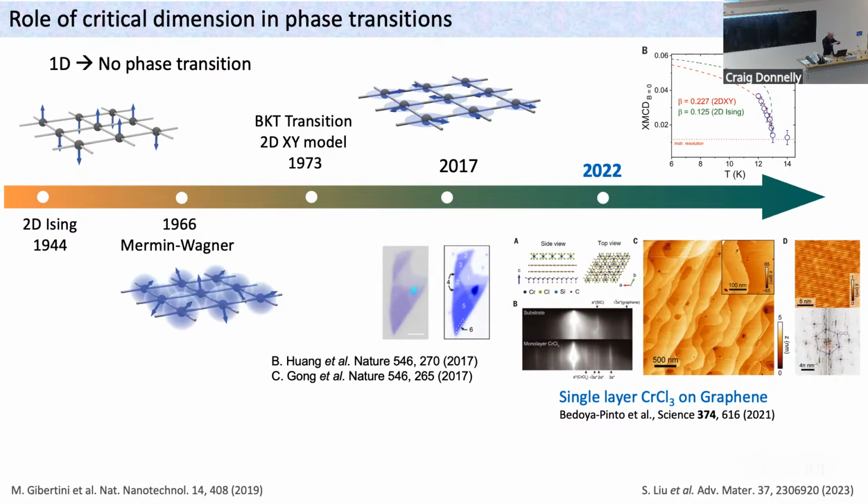So the magnetization can rotate in any direction. And moreover, by growing this by molecular beam epitaxy on large areas, it enables us to carry out measurements not otherwise possible. And we grew it on graphene, and it turns out there's no interaction between graphene and this layer. So it really is the first 2-dimensional XY layer.